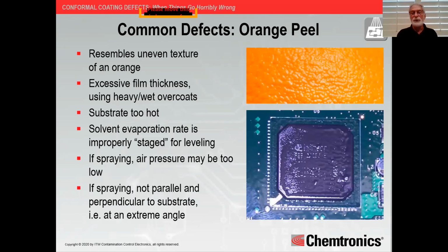Orange peel. It looks exactly like it sounds. Okay? It's a very rough, very uneven texture. You can see that. Actually, you can see the texture in the picture of the orange peel, but you can see it in that bottom picture on that component. Sometimes excessive film thickness and using heavy wet overcoats will cause this.